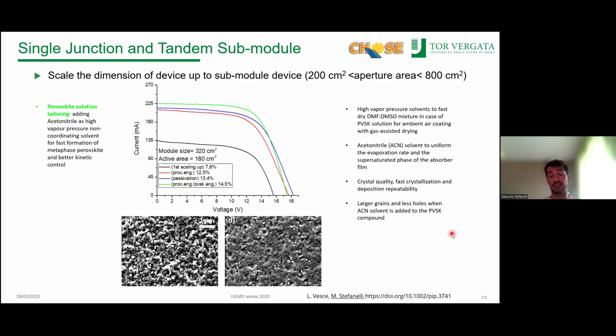due to the exposition of the first part of the film that we have at the start of the deposition, with respect to the end one that has just experienced the air for a small amount of time. So implementing the perovskite solution tailoring together with the process engineering that I showed you before, the best efficiency that we got for our modules with 180 centimeters square of active area is attested at 14.5%.